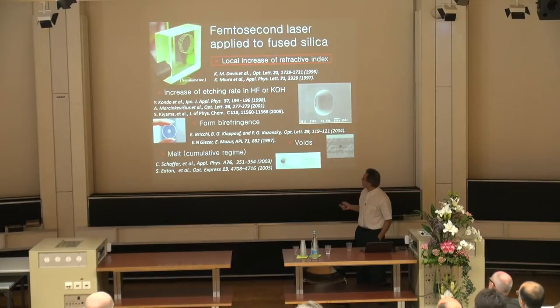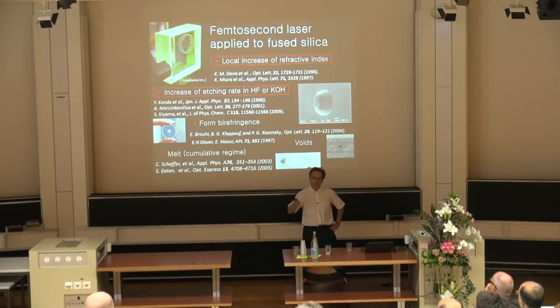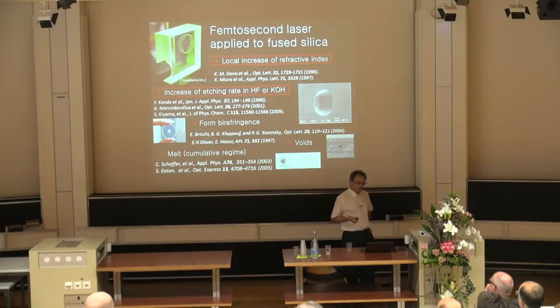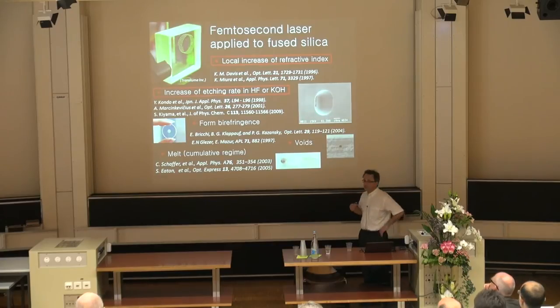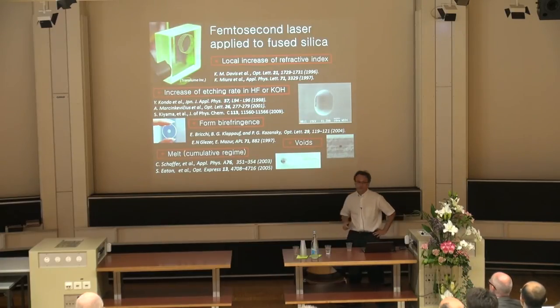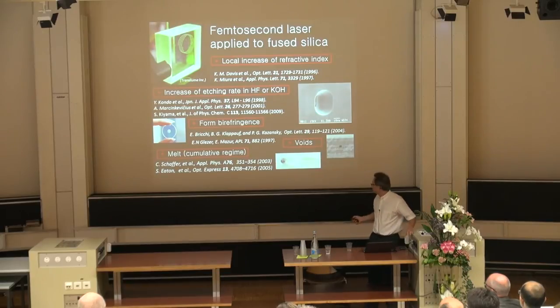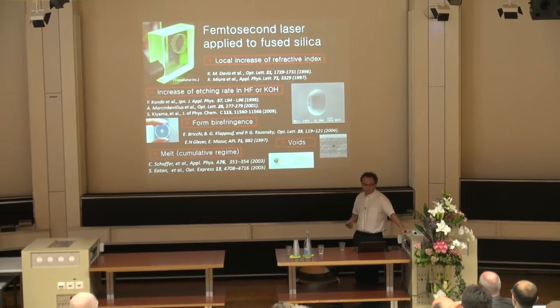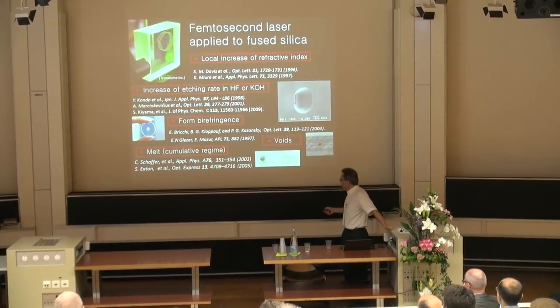Now, the second interesting thing is that whatever is exposed to the laser will be etched faster. So you get an increase of the etching rate in, for instance, HF or KOH, so that we can immediately think in terms of fabrication. And then there are other properties. I won't get into too much detail because this is more related to the optical properties, so controllable form birefringence, and eventually even creating voids, like you create cavities in the material. If you concentrate enough energy, it's almost like blowing it apart and creating a void in there. Or even melting the material if you concentrate a lot of energy at a very high rate.